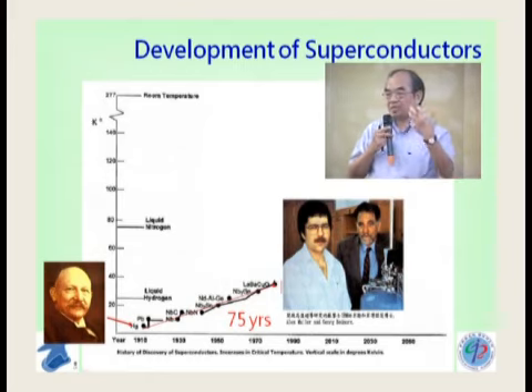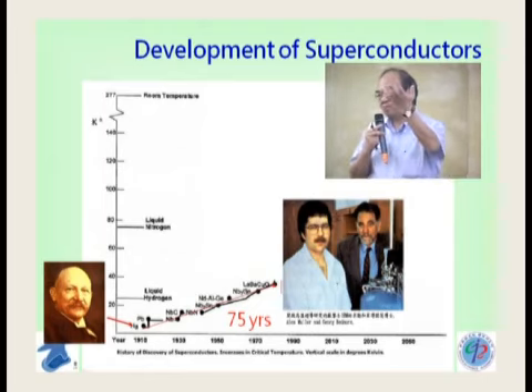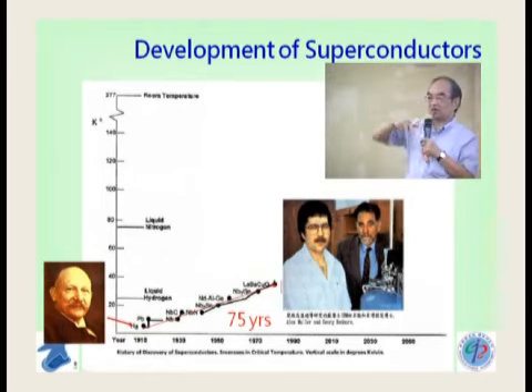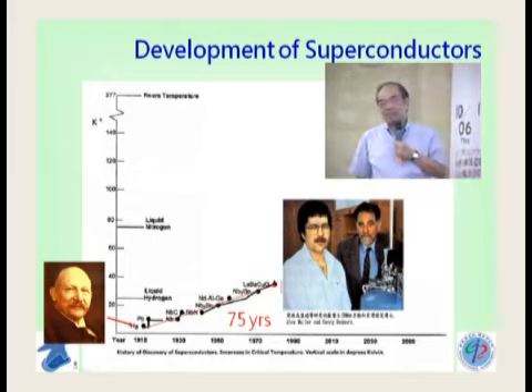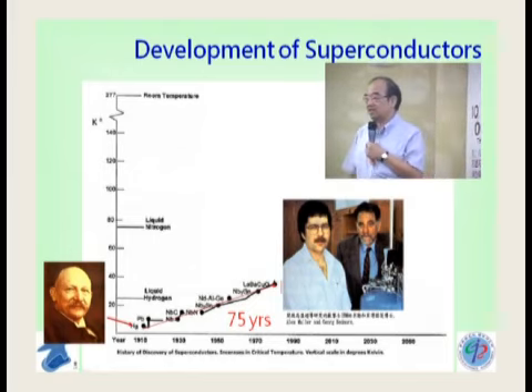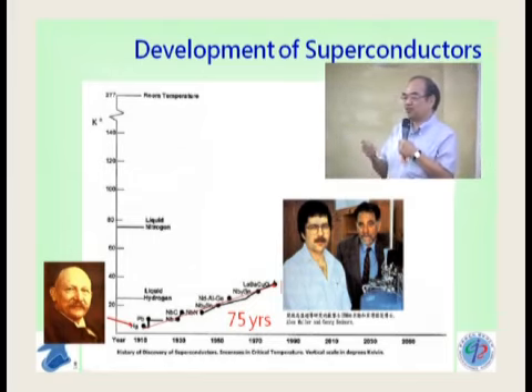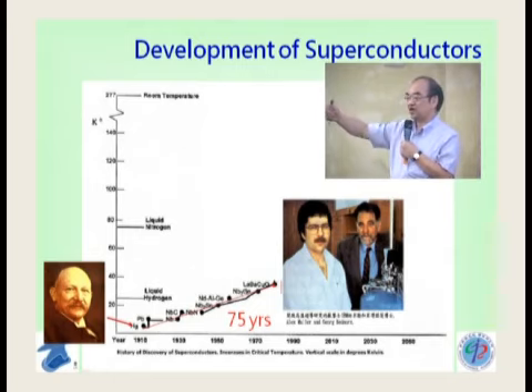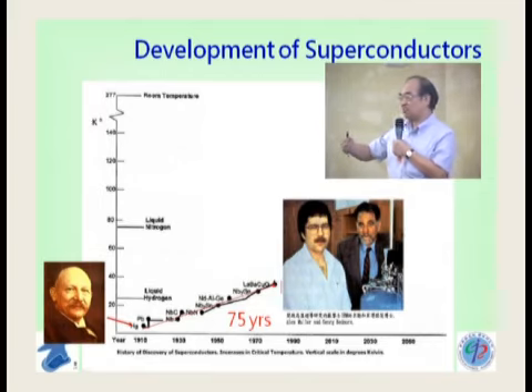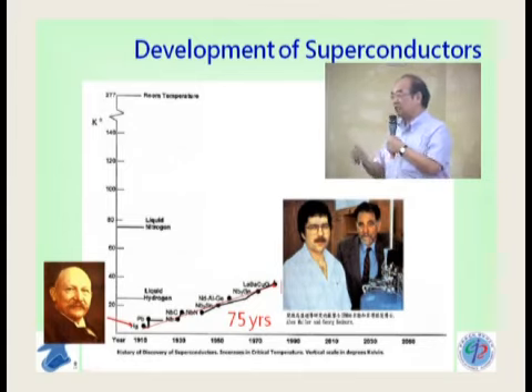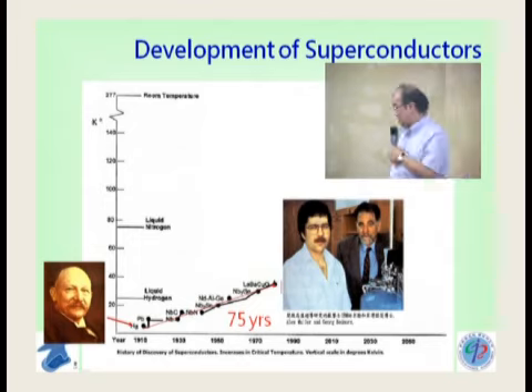And as you probably know, he found that with a little bit of pressure, the TC goes up, and then goes down, so it goes through a maximum. By the end of 1986, I was in Huntsville, and Professor Chu and I had an agreement. He would continue working with pressure, and I would start to look at the chemical way, using so-called chemical pressure, by substituting different elements to see how that would affect it. So we divided our efforts and pushed.